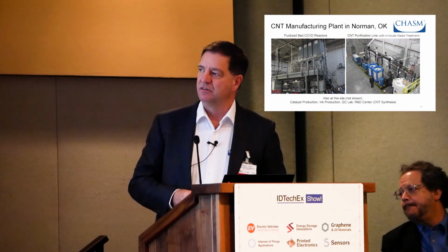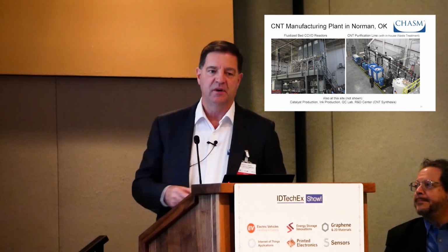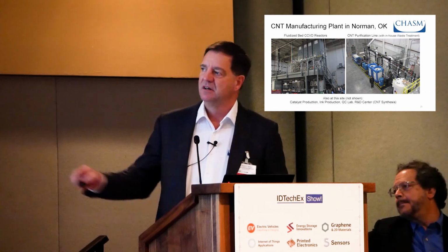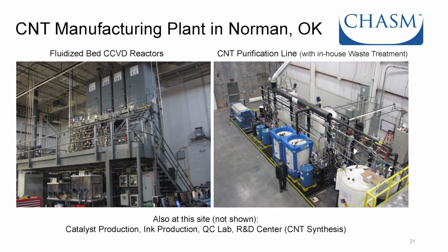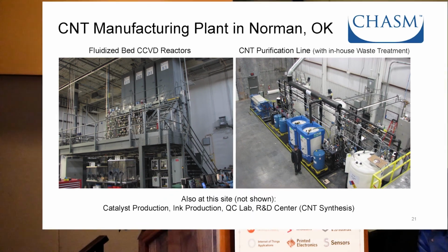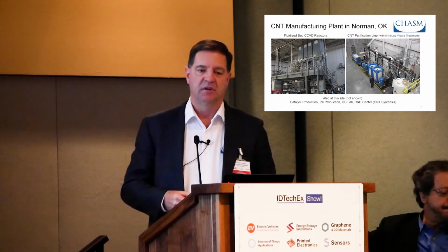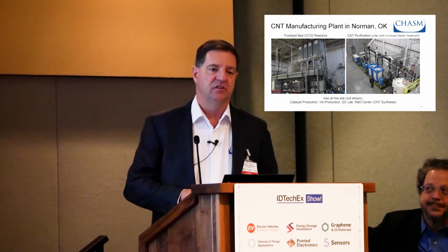This is just a few images of equipment we have in our Norman, Oklahoma plant. This is the scale. These are about 40 feet high, our carbon nanotube synthesis reactors. And this is our operation for purifying the carbon nanotubes to remove the catalyst material after synthesis, recover the carbon nanotubes, and then further process them into inks.